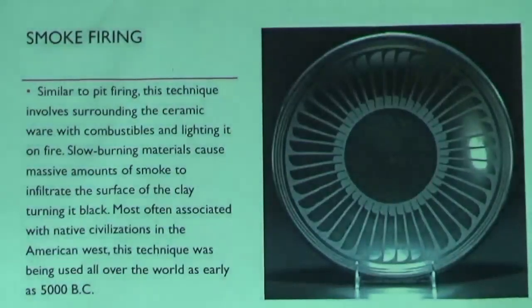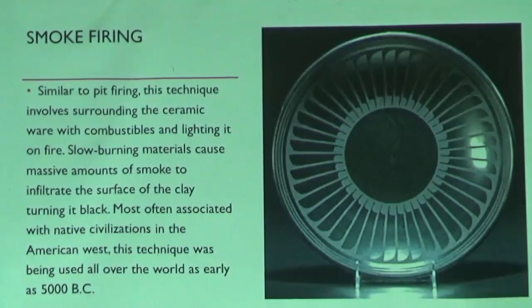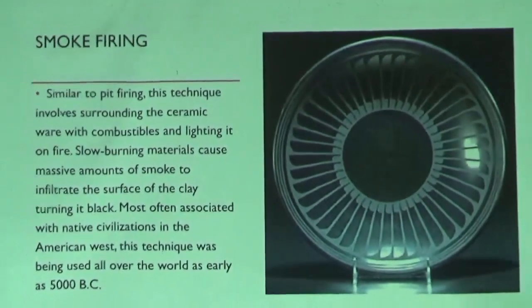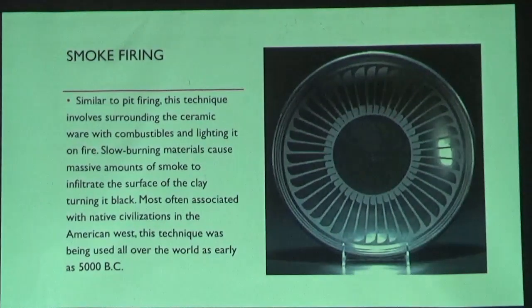Smoke firing, which I put on here, is similar to pit firing. This technique involves surrounding ceramic ware with combustibles and lighting it on fire. They would use slow burning materials, such as manure or straw, even sometimes damp straw, because that would create a lot of black smoke. Slow burning materials cause massive amounts of smoke to infiltrate the surface of the clay, turning it black. It's most often associated with native civilizations in the American West and in Mexico.